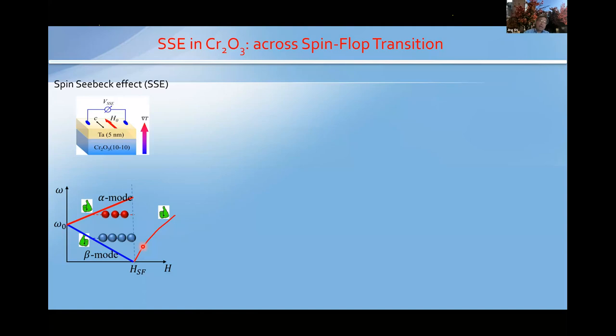So when you sweep field across this spin flop transition, one should expect a sign change in the spin flop transition. Okay, so this is somewhat one can do with manganese fluoride or chromium, but not with iron fluoride.